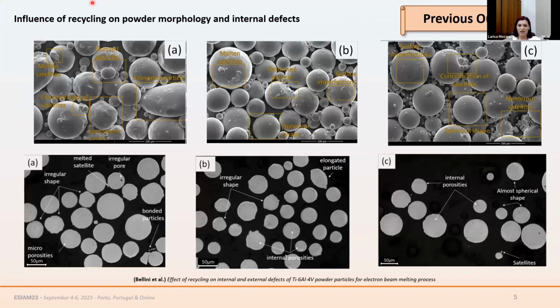We investigated the morphology and the external and internal defects of the powders. And here we can clearly see some differences between the virgin powders and the other two recycled powders. First of all, we have all of these tiny particles, which are called satellites. And this is detrimental for the powders because the flowability is decreased. But at the same time, we have an almost spherical shape and an almost smooth surface.